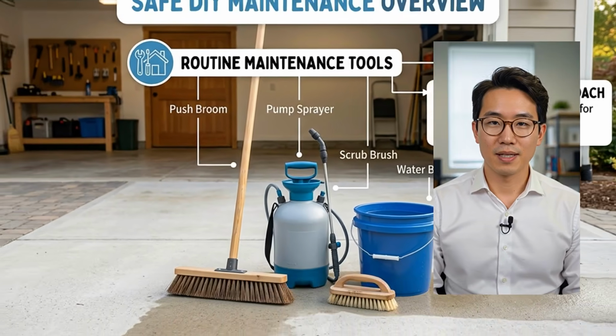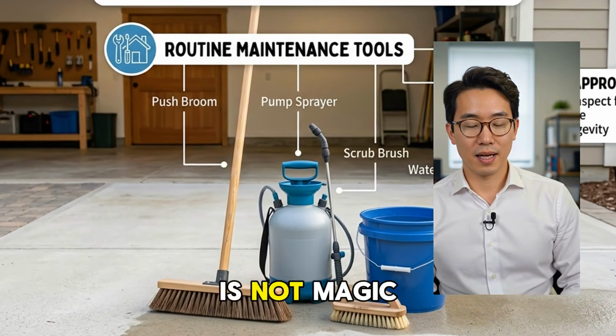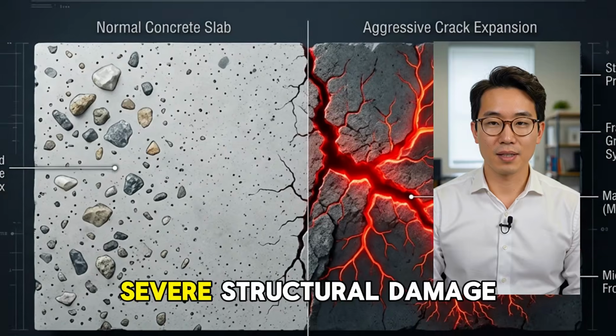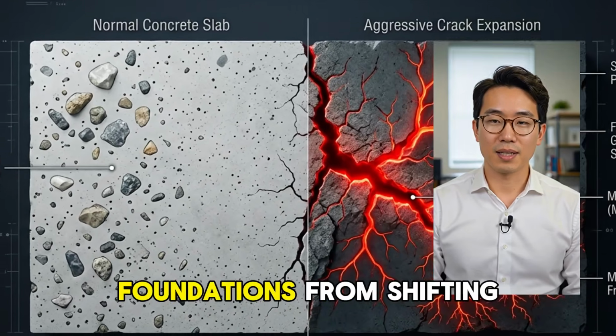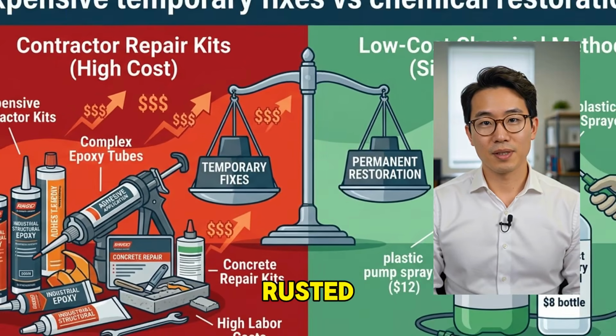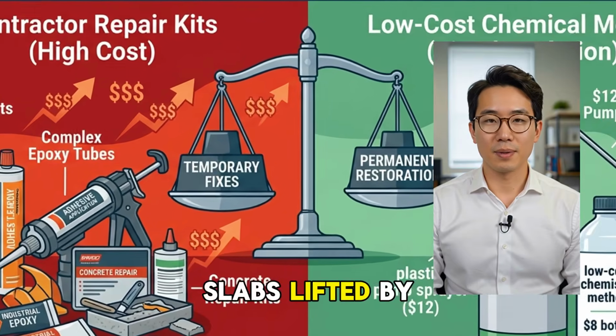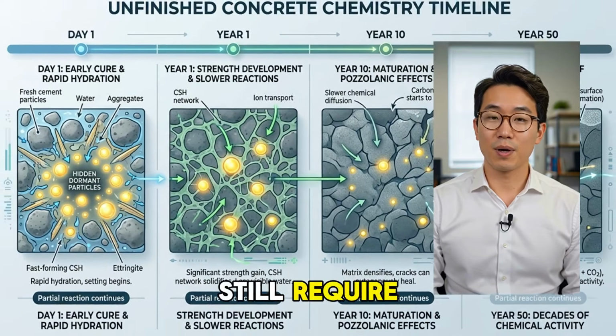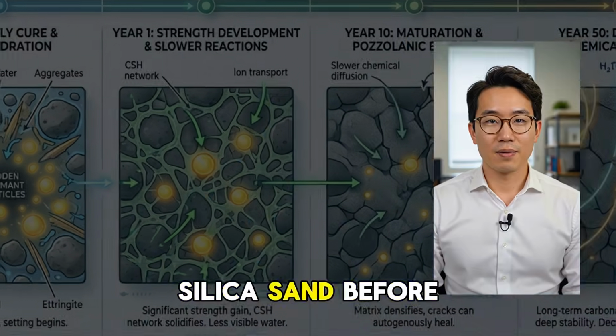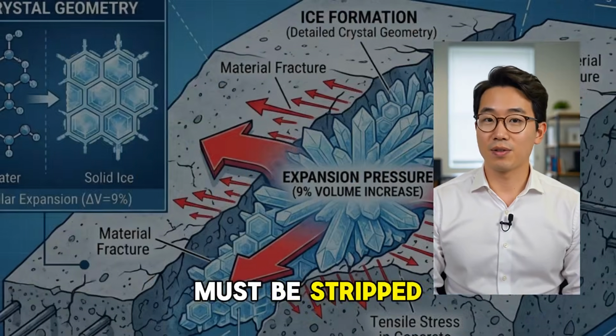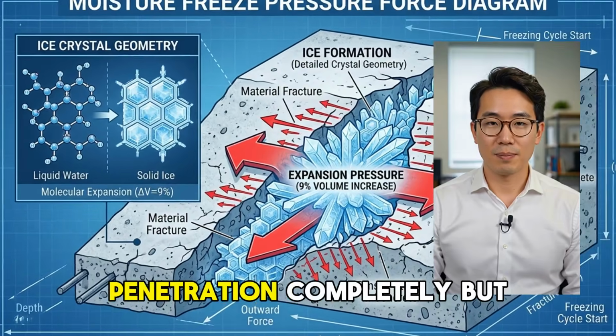Now listen carefully, because sodium silicate is not magic. It cannot repair severe structural damage. It cannot stop foundations from shifting. It cannot reverse rusted rebar or fix slabs lifted by frost. Wide cracks still require filling materials or silica sand before treatment, and surfaces covered in epoxy or acrylic sealers must be stripped because coatings block penetration completely.